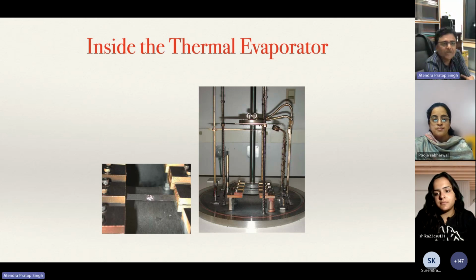The film thickness deposition accuracy depends on the method by which you are measuring it, like the QCM. Suppose I'm using the quartz crystal microbalance. They are highly accurate. Normally you can get up to angstrom level thickness, a few angstroms only. They themselves are very accurate, but you have to calibrate them every time for the material in the controller. But they are very good, you can get a few angstroms, so the thickness can be told very accurately. This is because they are based on resonance phenomena, so a small shift can be detected.